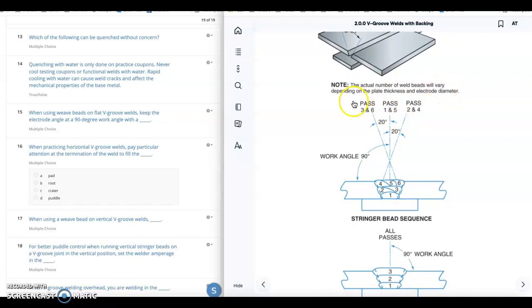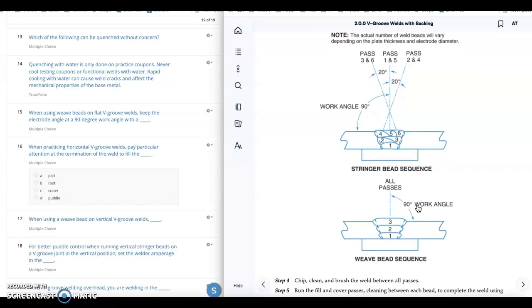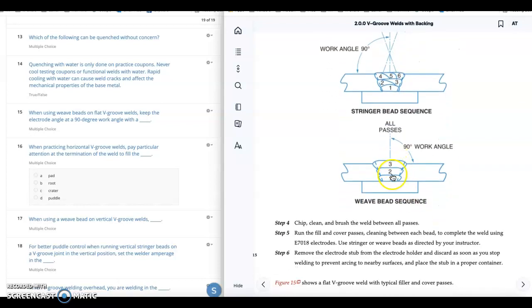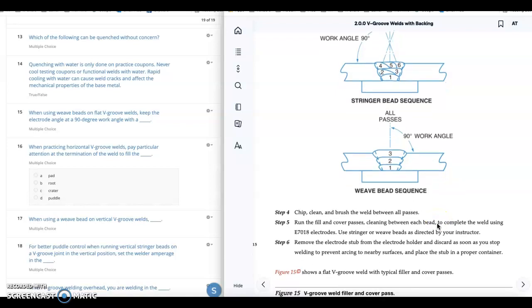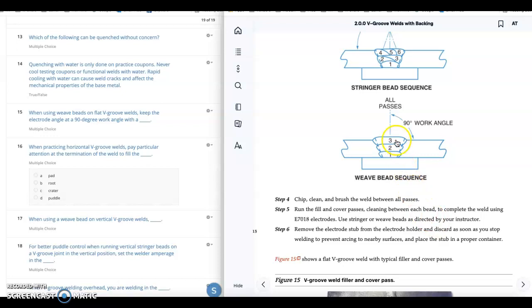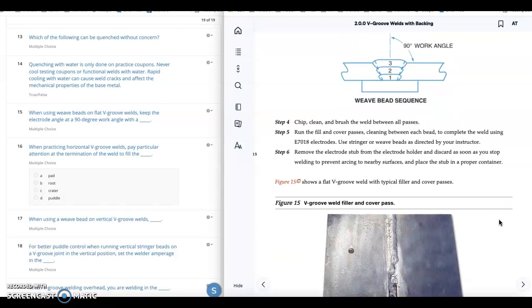Actual number of weld beads vary depending on plate thickness and electrode diameter. We use a 3/32 welding rod, so you're going to look at 6 passes. Root, fill, cap. That's what you should expect. These 1, 2, 3 are not acceptable for the welding competitions. If there's a new WPS, if it's not out yet, it's coming out. We're not going to practice this because that's going to handicap us if they force us to do a multi-bead cap.